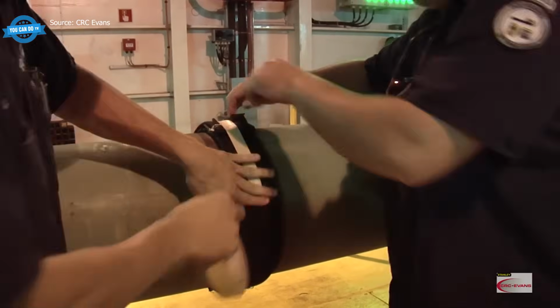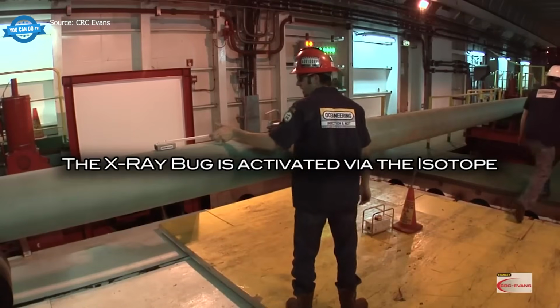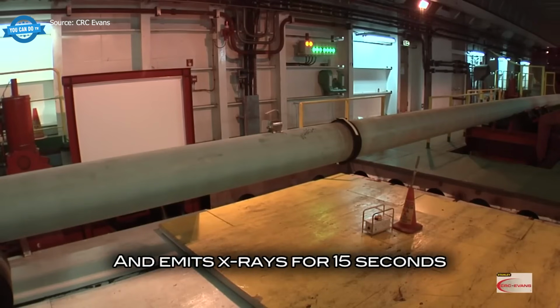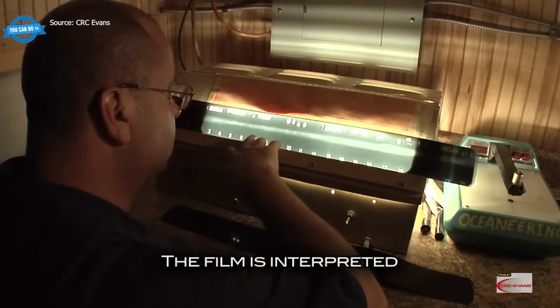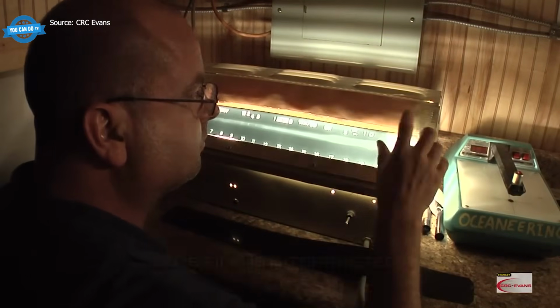The completed weld then moves to an automated X-ray testing booth where every millimeter of the weld is imaged and reviewed before the pipeline is allowed to advance any further. One bad image stops the entire firing line until the joint is reworked or cut out.